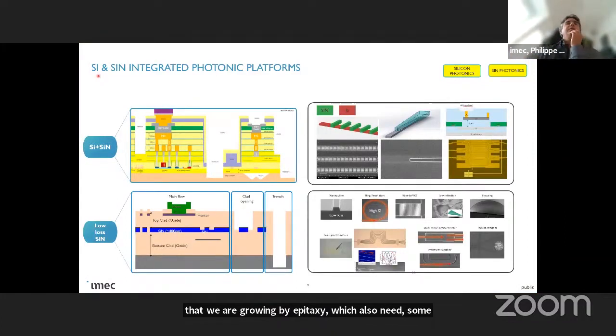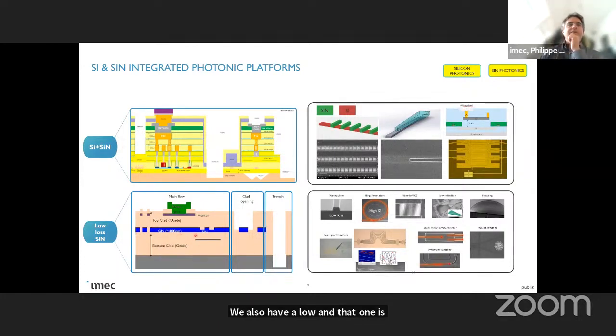This is the first platform, where you can see we are stacking the SOI, we are putting the silicon nitride, and then we have back-end of line types of processes that we are running. We also have a low-loss silicon nitride, and that one is the high-temperature nitride, which goes into the dB per meter range usually. So for some applications, specifically in quantum, they are really chasing the photons. And we do use this platform for this kind of application where the losses are extremely important.